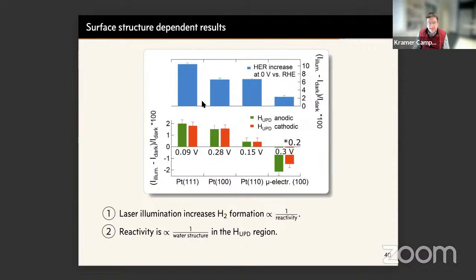And what you see quite clearly is that the largest effect on H2 formation is for platinum 111, then 100, then 110, then the microelectrode at its 100 feature. We just happen to measure it there. Interestingly, now, if you look at this UPD feature, if you pick your favorite UPD feature on these 3 surfaces, one sees that the size of this effect decreases as you go from 111 to 100 to 110, and for the microelectrode, it actually flips sign.